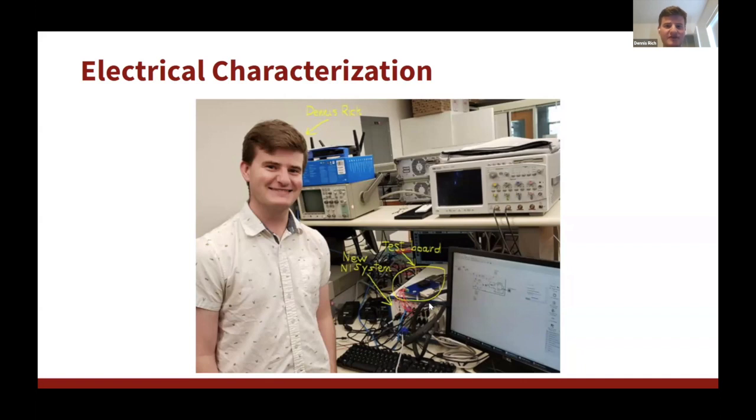But in terms of what's holding us back, I guess part of the answer is something called endurance. That's maybe one of the big challenges in a lot of these new emerging memory technologies today, and that's how many times can I write new data to this memory cell before it breaks. If you're optimistic, the answer for phase change memory is usually about 1 billion times.